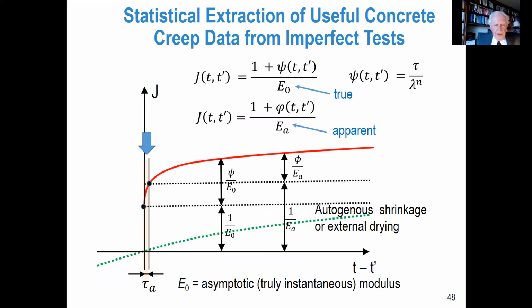So how can we measure it? Important is the initial behavior. So you have a creep curve which starts with a vertical tangent. It is difficult to say where the creep begins, what is elastic. Consider this pink strip. So it's about 1 or 2 days. If we have other phenomena going on, inevitably autogenous shrinkage always goes simultaneously. We have two phenomena going here, creep and autogenous, they interact. We cannot say anything simple.